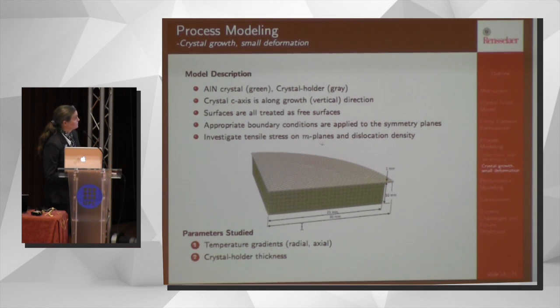So here's a sort of schematic of our model. We have the crystal that's growing. This is the crystal holder above, typically tungsten. The crystal is grown along the C-axis. It's hexagonal. The aluminum and the nitrogen each form HCP lattices that are intertwined with each other. The surface is treated as free, and the main metrics that we're interested in are the tensile stress on the M planes, those are the cleavage planes, and the dislocation density. So we want to keep both of those quantities low. And we wanted to see what the effect of temperature gradients and the crystal holder thickness are, and their relative importance.